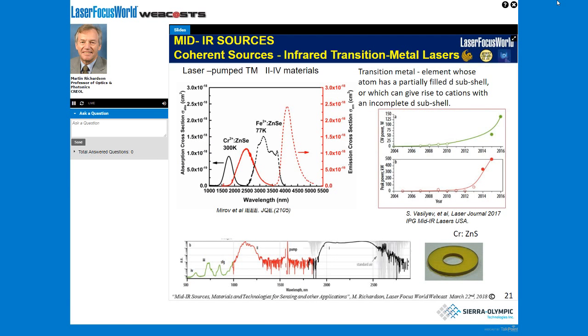Another way of producing infrared laser light sources is to use transition metal lasers. This is being pursued in a number of laboratories, but I want to just refer briefly to Mirov's group at the University of Alabama. The most successful data so far seems to be with chromium or iron-doped zinc selenide or zinc sulfide host materials, in most cases pumped by erbium lasers at 1.5 microns.